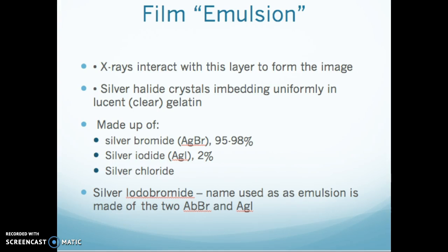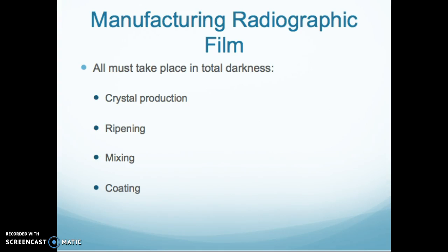So silver halide crystals are embedded uniformly in this clear gelatin. The crystals are silver bromide, about 95 to 98 percent depending on the manufacturer. Silver iodide is about 2 percent, and sometimes there's silver chloride in there. Silver iodobromide is the name used for the emulsion, made of silver bromide and silver iodide. Now I'll show you the structures.